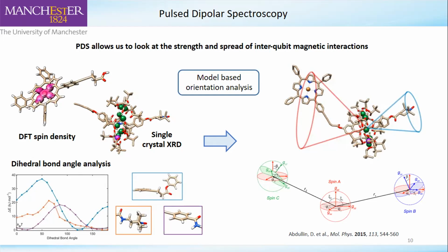So what we did first, instead of just doing DEER and analyzing it orientationally independently, was a model-based orientation analysis of the 3-spin system, where we took DFT spin density calculations combined with single crystal XRD, and a dihedral bond angle analysis of the dihedral angles in the molecule, to build this model of where our spins would be expected to turn up in space relative to each other.